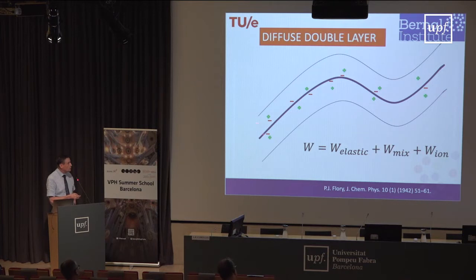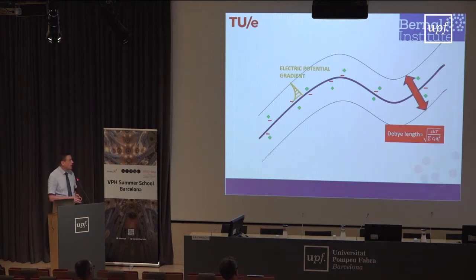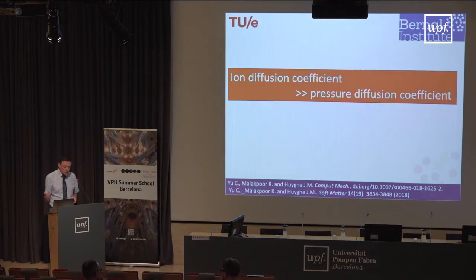So we have basically a double layer around every protein or every polymer, with negative charges and compensating positive charges in the fluid. This is basically what generates most of the ionic swelling, namely around the positive charges, there are a lot of water molecules. And we can talk about the Debye length, namely the thickness of that double layer, which becomes larger as the outer salt concentration becomes less, and smaller if the outer salt concentration becomes more. Now, in gels, unlike disc, you can say that the ion diffusion coefficient is typically much larger than the pressure diffusion coefficient. Why? Because the pressure diffusion coefficient is linked to the stiffness, and because the stiffness is so low, you get a low pressure diffusion coefficient, much lower than the ion diffusion coefficient.